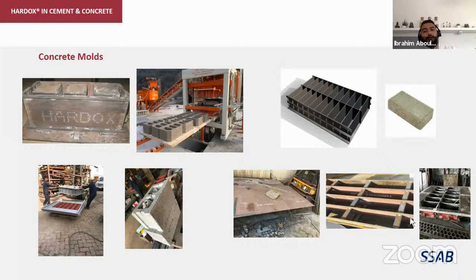In some other cases, we have longer times for vibration, but very low frequency, which can get to 2 minutes of vibration. For that case, we recommend Hardox 450 or 500 tough, since the impact toughness will also not be reached. For the Hardox 600, you can reach up to 1 million concrete blocks. And for the other solution, for the 450 and the 500 tough, it's more or less also the same.